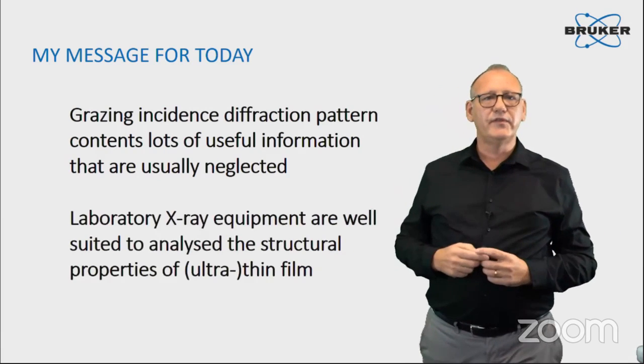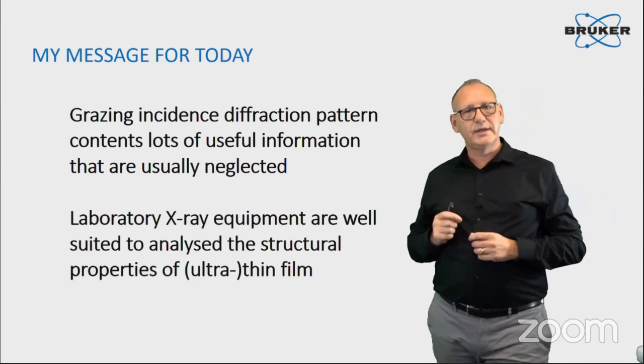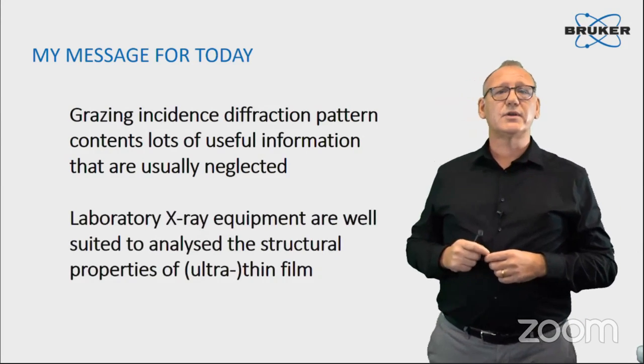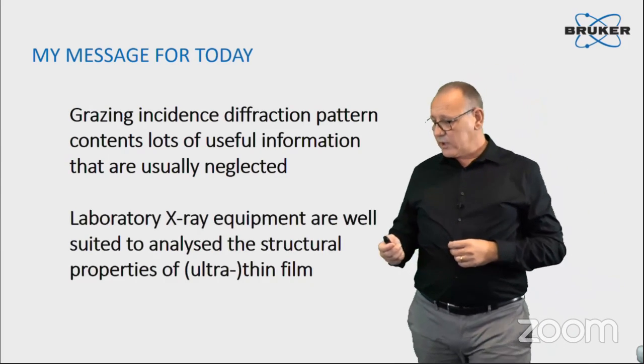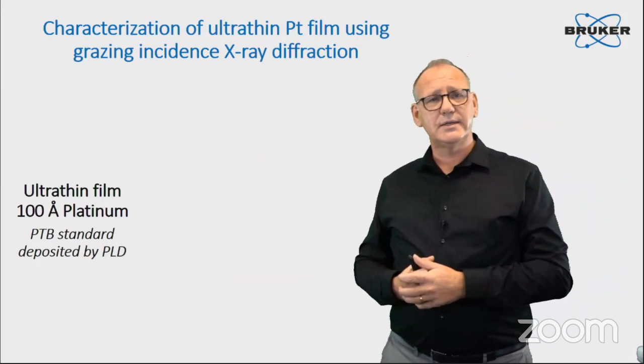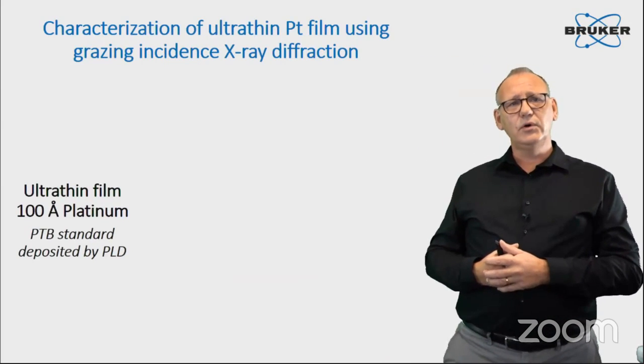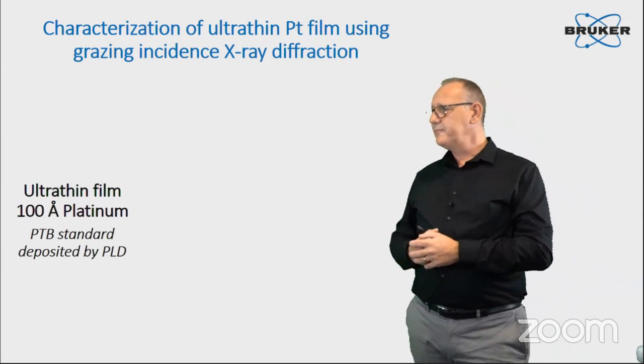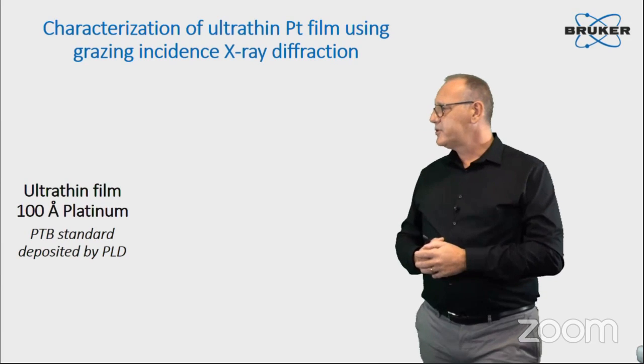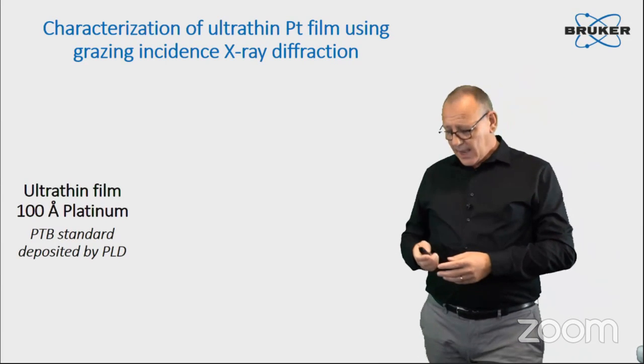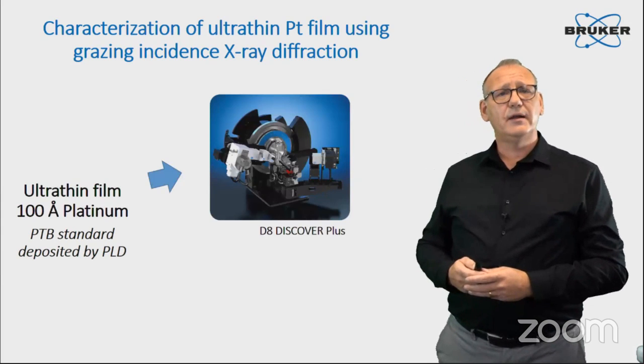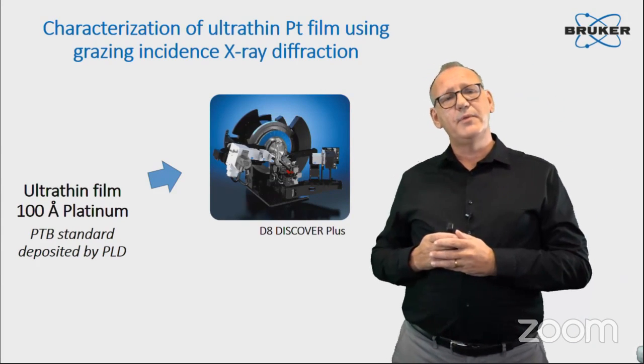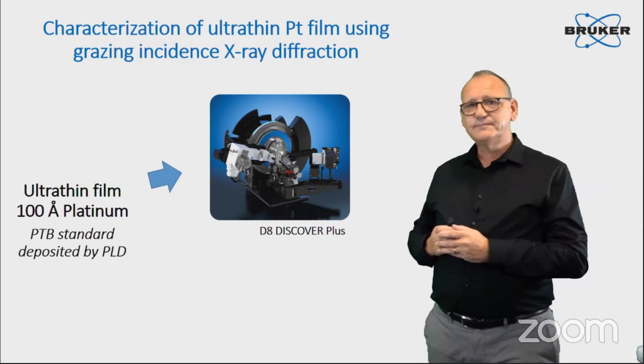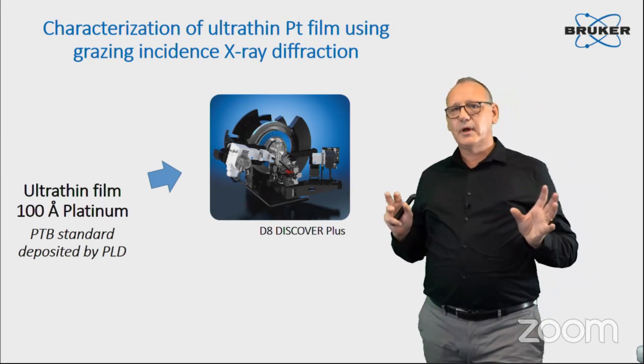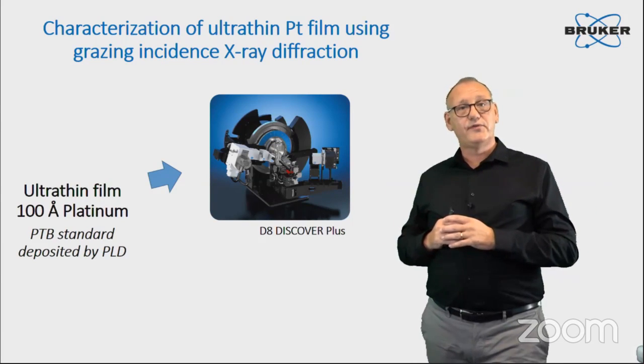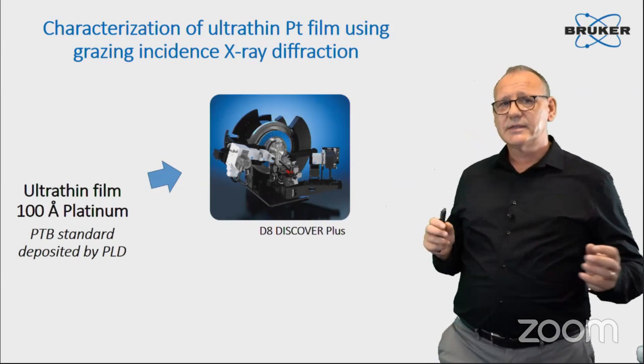This is the next point I want to convince you of: laboratory equipment is well suited for analyzing the structural properties of those ultra thin films. So what we are going to see during this talk is the investigation of an ultra thin film of 100 angstrom of platinum. This is a standard from PTB, deposited by pulsed laser deposition. And we are going to analyze this film with a newly released equipment at Bruker. This is the D8 Discover Plus, which will allow setting up dedicated diffraction geometry for thin and ultra thin films with different scanning directions.